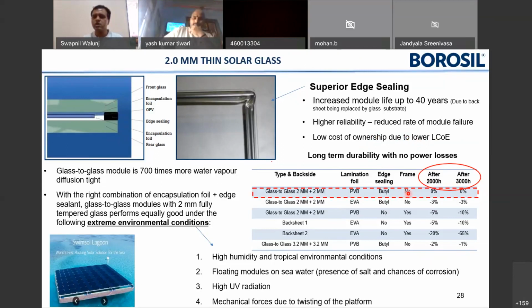Because if you see various modules, glass to glass, used with the normal glass as well as the glass with backsheet, and you do these accelerated tests, the PID at the end of 2000 hours or 3000 hours is lowest if you use 2 mm glass in front and back and use a proper edge sealing material like butyl. You get a glass which is most reliable.